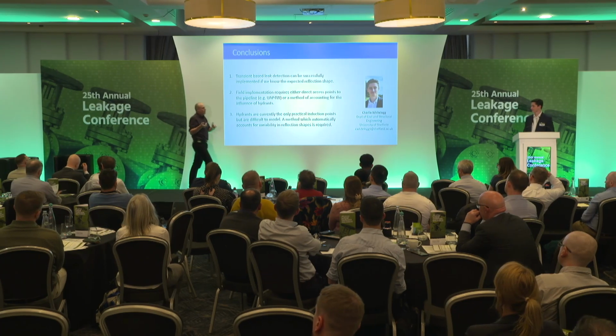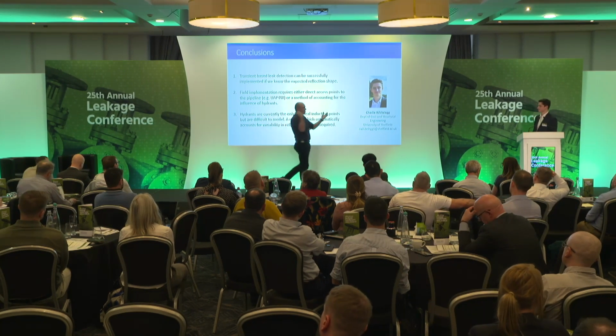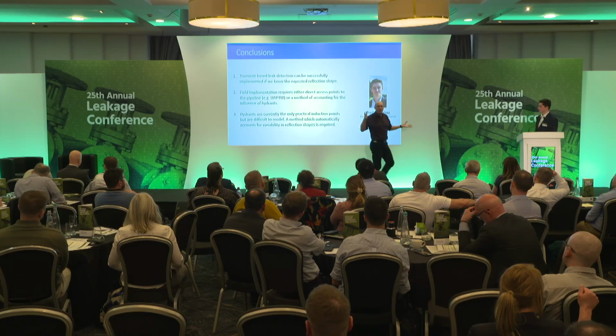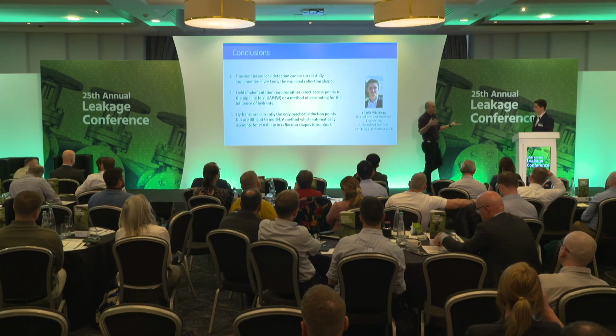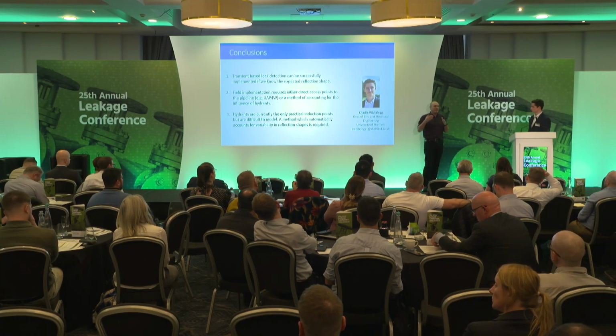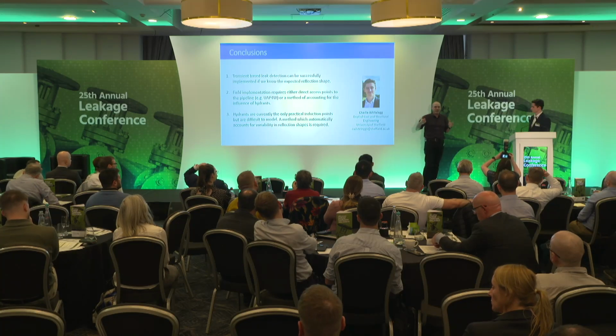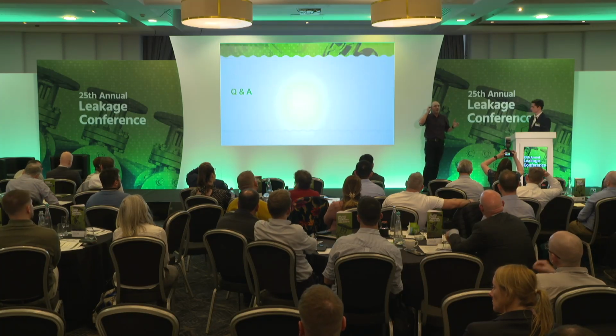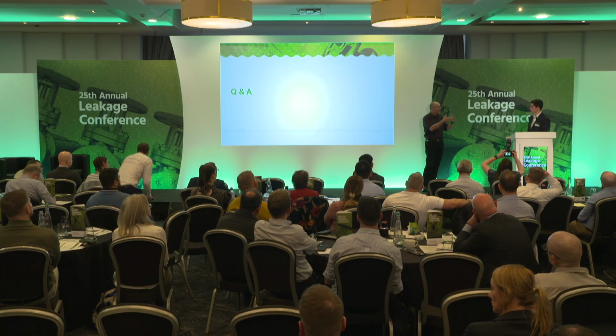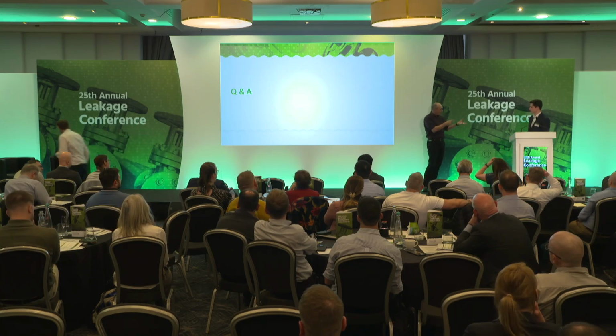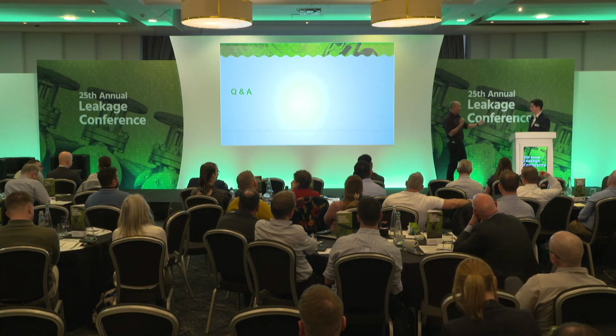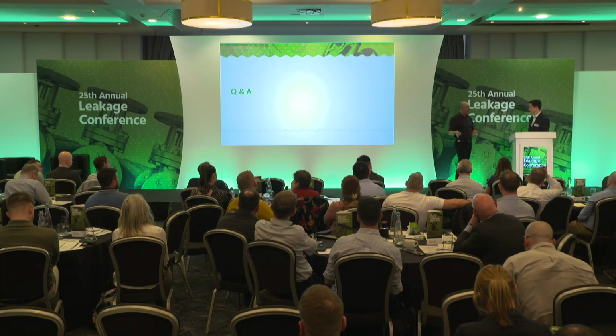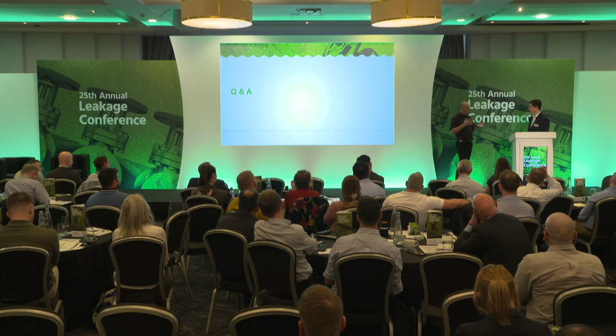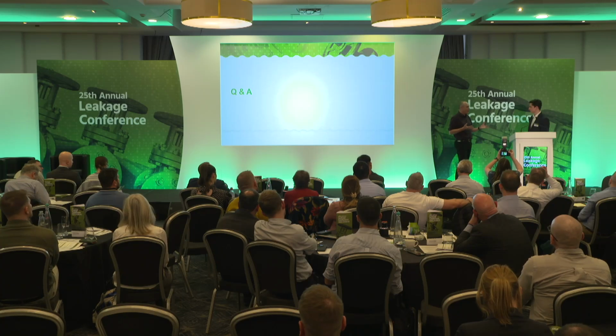That's really interesting. So we've known about this kind of sonar effect. At the moment, if we're looking for leakage, particularly on plastics, in the past we tend to be passive. It's like when you think of submarines and they're listening for the sound of the submarine, and then you get the active sonar ping, the other way of doing it. So we've known about that, and we've known that that's coming through as a technology. But what was really fascinating was the effect about hydrants, which I will be absolutely honest was how we were planning on introducing it and showing the kind of problems associated.